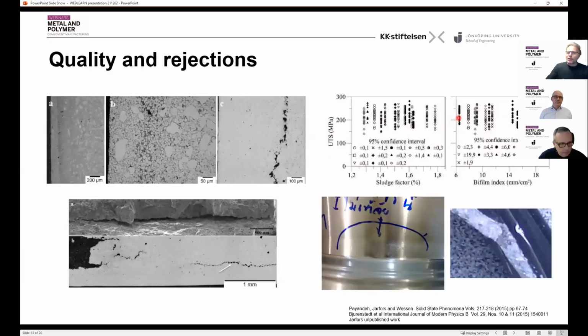So the thing that happens when you have greater material losses during your transfer, you have more slag to manage. It's not just the material loss, you have more material that can go into castings. And you can have cracks being formed, you have oxide layers, and they are also on the macroscopic scale. This is from a wheel, and all the mess here is essentially large oxide.